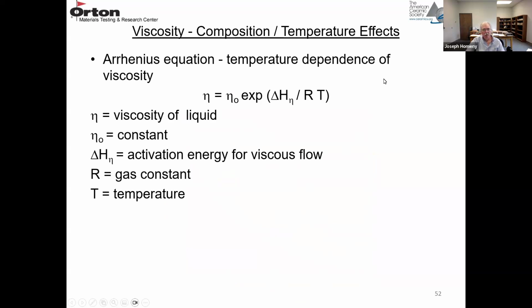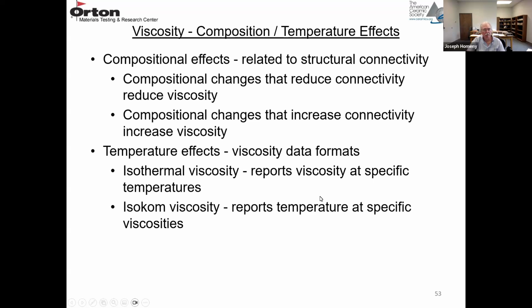So viscosity is temperature dependent. It follows this Arrhenius equation. So eta, the viscosity of the liquid, equals eta 0, which is a constant, times e to the ΔH_eta divided by RT. ΔH_eta is an activation energy for viscous flow. R is the gas constant and T is the temperature. So this is the Arrhenius equation. If you increase the temperature, the exponent gets smaller, and then the viscosity goes down, and you have a more fluid liquid. So increasing the temperature lowers the viscosity as an exponential relationship.